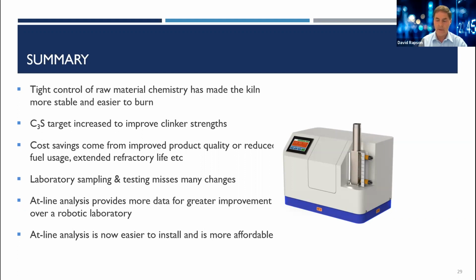The increased sampling frequency of the raw meal revealed variations that could not be seen with standard laboratory testing. The additional at-line data included the kiln dust and the raw mill recycle material, which gave more accurate control of the feeders, further reducing variation. The at-line analyzer has shown that it's an essential tool for stable kiln operation and has enhanced the clinker quality as well.